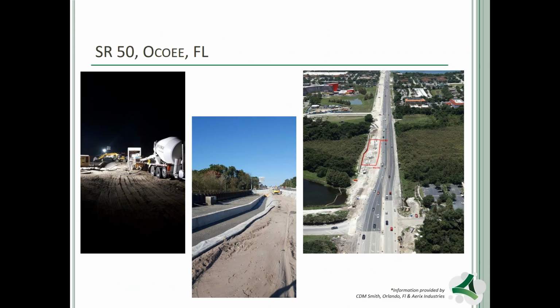On the project that was done, actually just northwest of Orlando, is soft soil remediation, where they wanted to lighten up the load on a road widening project in the marshy area. They drove the sheet pile walls and then tied those back into a retaining structure, and then did the backfill. It was 3,000 cubic yards. They utilized ready mix trucks on that, and they completed that project and the backfill in 2.5 evenings. And it was done during the evening to make sure that there were no ready mix trucks during the heavy traffic hours. I'll get back to vertical retaining structures here in a minute, because that driven sheet pile wall is actually a little bit over engineered, and I'll show you why.